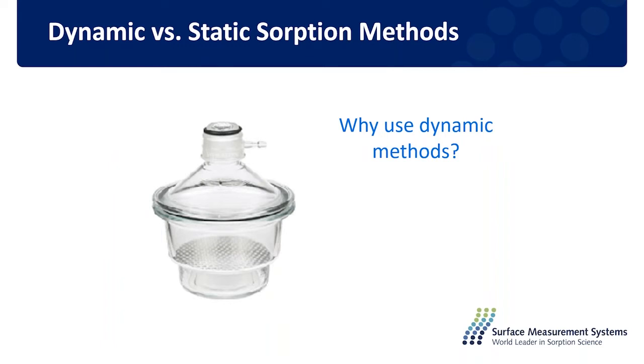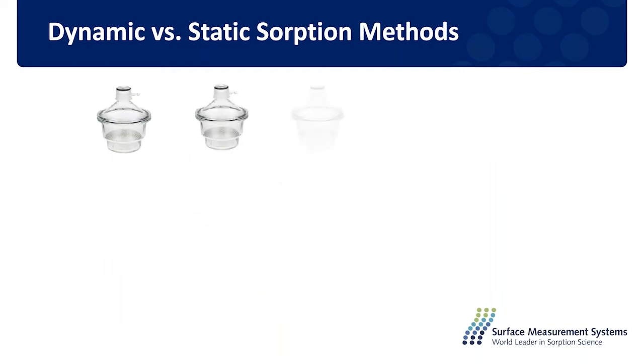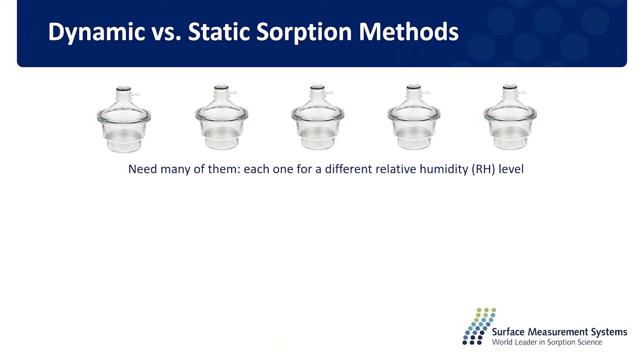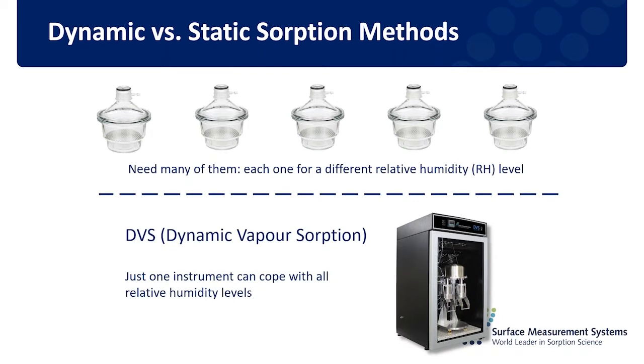So compared to the traditional sorption method, why are we using the dynamic way of vapour sorption? The traditional method is known as the jar method, where each jar represents one relative humidity. We need to put the sample in the jar, wait a very long time for the sorption to be established, and then take the sample out for the measurement. In the dynamic method, we have a continuous flow of the probe molecule and a constant measurement inside the system, so we can get a much faster and also more accurate result.